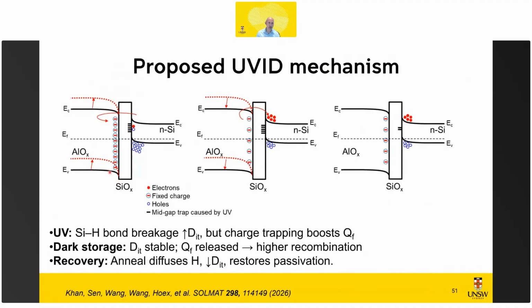UV-induced degradation breaks silicon-hydrogen bonds. In the whole dielectric stack, this hydrogen piles up at the interface and creates defects. But the UV also increases the fixed charge density in AlOx. One effect is making surface passivation worse, the other is making passivation better, but the overall balance is that passivation gets worse, so you get higher degradation. In the dark, this high amount of charge that you've pumped during UV exposure goes back, and that is the main cause of the dark storage effect. This is completely reversible. I will show you the dynamics in one of the next slides. The recovery that we see, and what we also hope to see in the field, is that the hydrogen that piles up at the interface leaks away. It can leak into the bulk, and then your interface is restored.